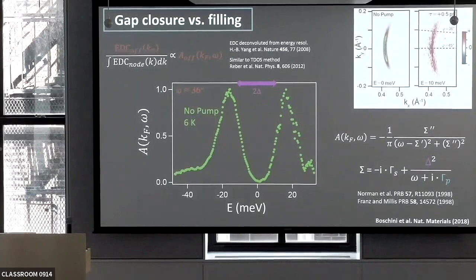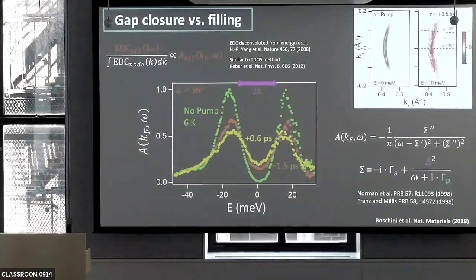Now the question is, you come in with a pump, what's happening next? Is it the closing or is it filling? And here are the data. You see a little bit of a change in the gap itself, but mostly the biggest change is in the filling itself. So it really is a broadening out of the peak, and the gap almost doesn't change. And if you wait for time to come back, then of course over time the system will go back to the original state. So the conclusion of this work directly is there is no gap closure, there is a filling, so the dominant parameter here in controlling superconductivity appears to be the phase coherence itself.